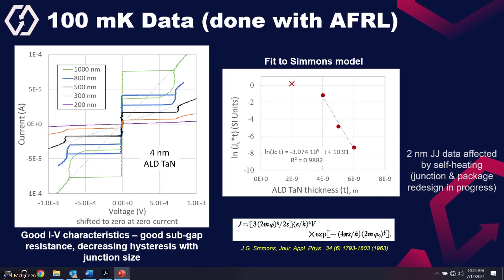So here we measure the current versus voltage curves for a junction with 4 nanometer ALD tantalum nitride in the barrier for different dimensions. In this curve, when it is in superconducting state, the resistance is 0, and at the critical current, it switches to the normal state. The voltage at which it switches is known as the characteristic voltage, which is about the same for all the dimensions of the junction. And the linear curve goes through the 0. So this determines that this acts like a good junction, and the IC varies as a function of dimension.